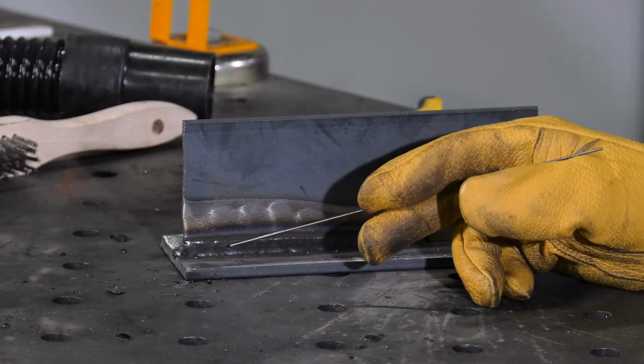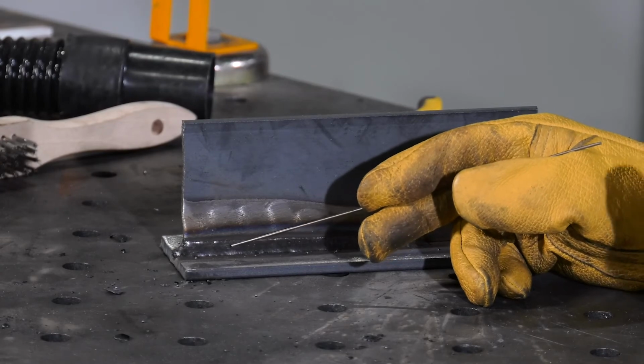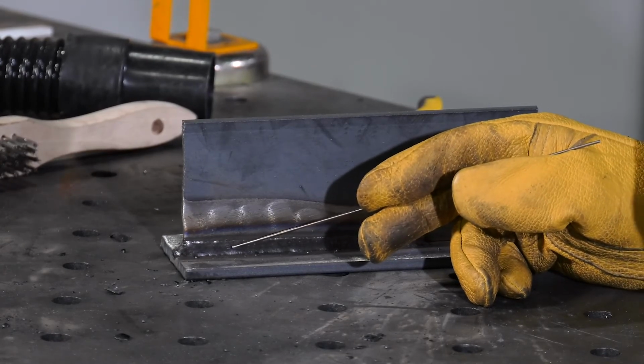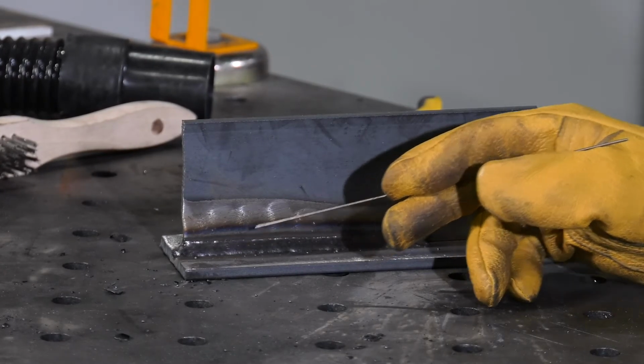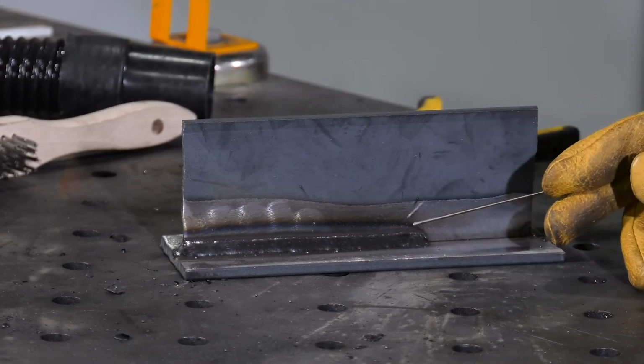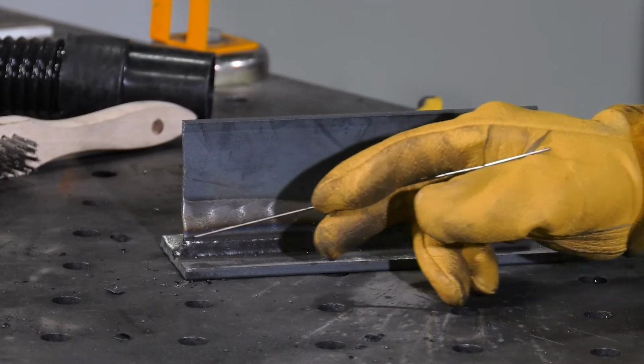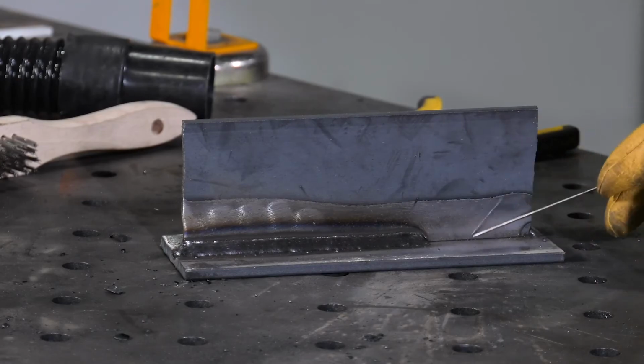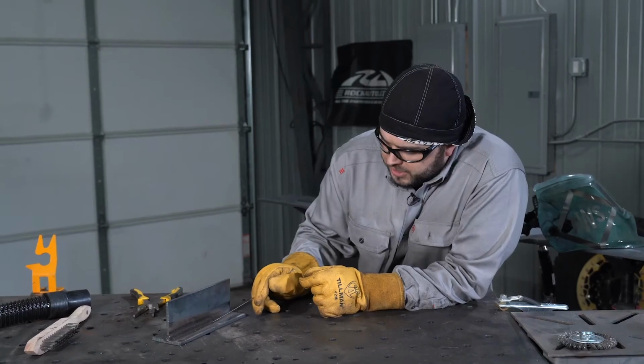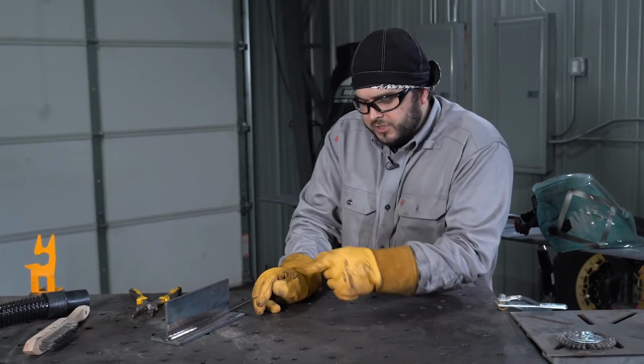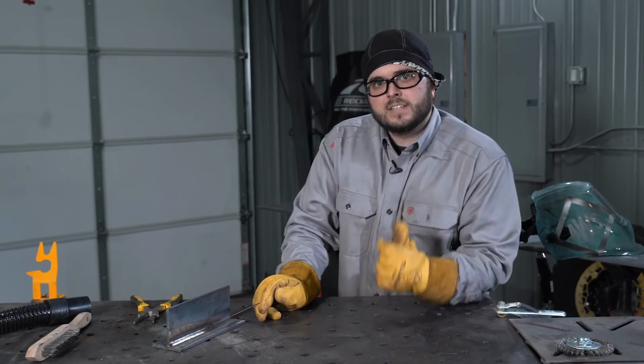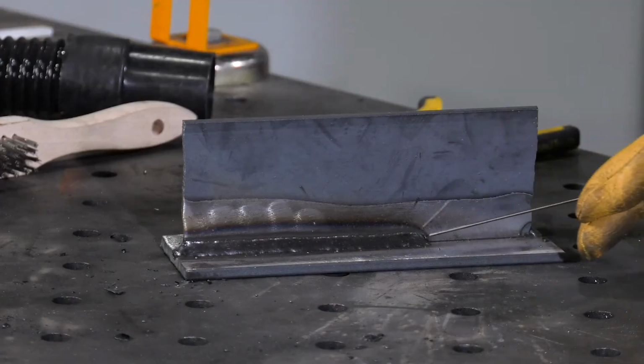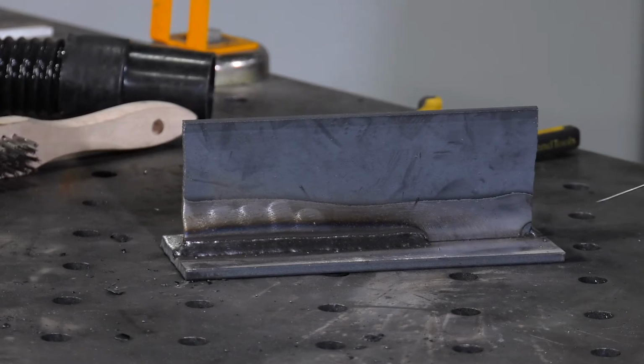Also, it's really important to make sure that your contact tip to work distance is maintained about 3/4 inch. If you get too far out, you might see some porosity. If you get too close, you might see worm tracking or a squirrely looking bead. If you start to see undercut, make adjustments in your travel angle or the settings on the machine. When you get to the end of the weld, pull off, take a look, and adjust from there.